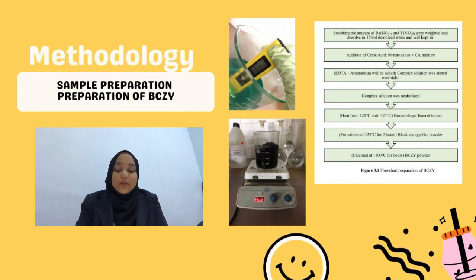After that, the solution was heated and stirred for a few hours on a heating plate at 120 degrees Celsius. This is to get rid of water until a brownish gel is obtained. The gel was dried and pre-calcined at 325 degrees Celsius for 2 hours, and then calcined at a temperature of 1100 degrees Celsius for 10 hours with a rate of 10 degrees Celsius per minute.